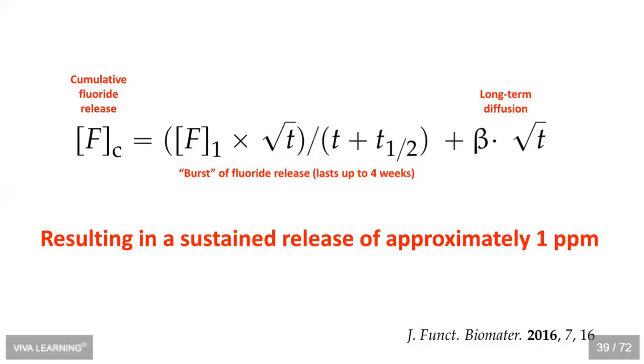There's going to be an initial burst for about a month, and then you've got this long-term diffusion of fluoride ions into the tooth, which gives you this total cumulative fluoride release. And if you keep adding things to those materials, you can supercharge them and just keep driving this concentration up. And like I said, recharge those things with remineralizing solutions with things like fluoride varnish. Francisco Ramos Gomez out at UCLA, the guru of pediatric dentistry out there, I call him the Pablo Picasso of pediatric dentistry. Francisco's been doing what he calls the GIFT study, the glass ionomer fluoride treatment study, where he puts glass ionomer on teeth and then fluoride varnish to supercharge them, and is showing caries resistance.